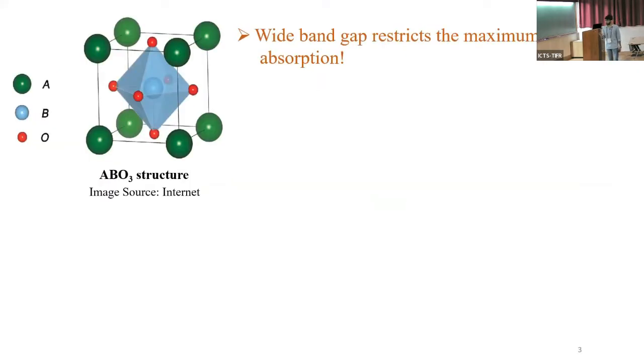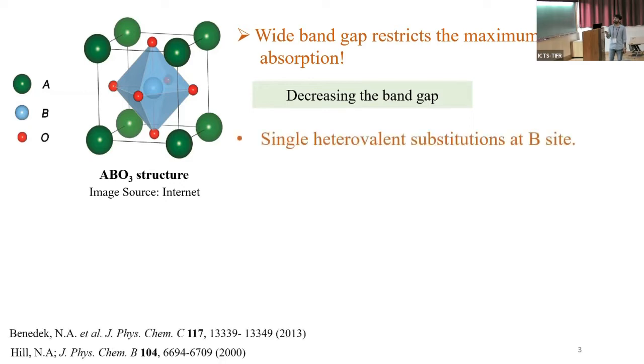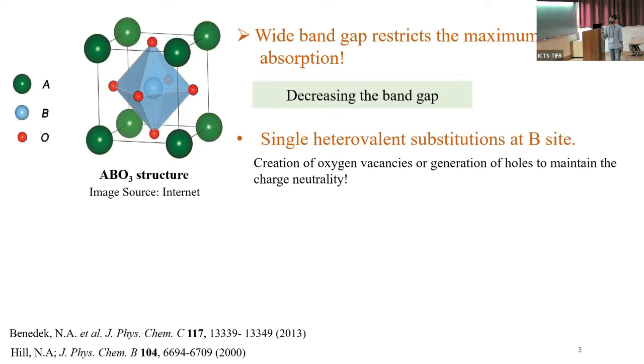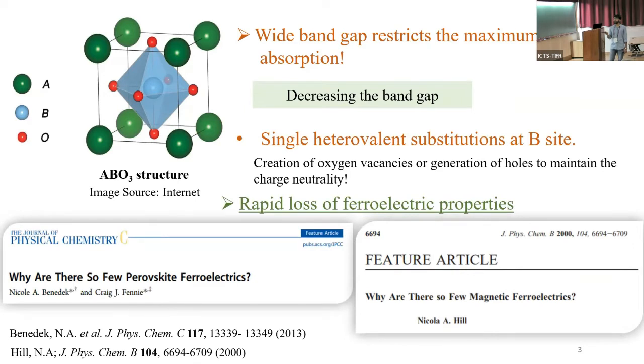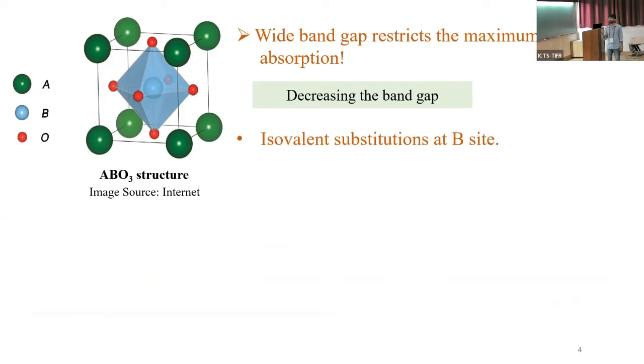The problem with ferroelectric materials is that most stable ferroelectric materials available today are perovskite oxides having ABO3 structure. Now, perovskite oxides come with a wide band gap, which restricts their maximum solar absorption. To use ferroelectric materials for photovoltaic purposes, one has to decrease the band gap. The most viable approach is to use a single heterovalent substitution at the B site of the perovskite structure. But these single heterovalent substitutions mostly create oxygen vacancies or holes in the system to maintain charge neutrality, and it has long been known in literature that such substitutions lead to rapid loss of ferroelectric properties. So one then goes with isovalent substitutions at the B site.